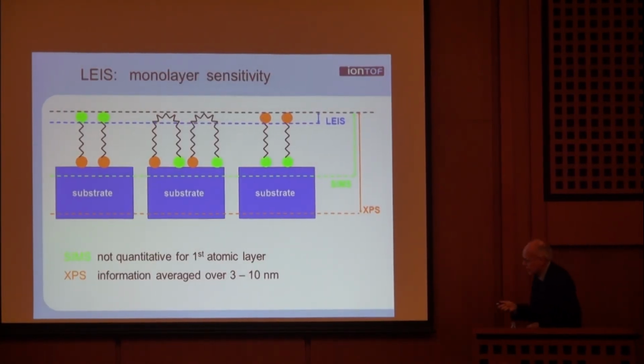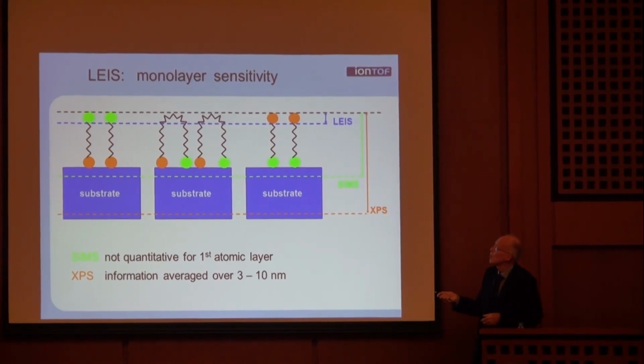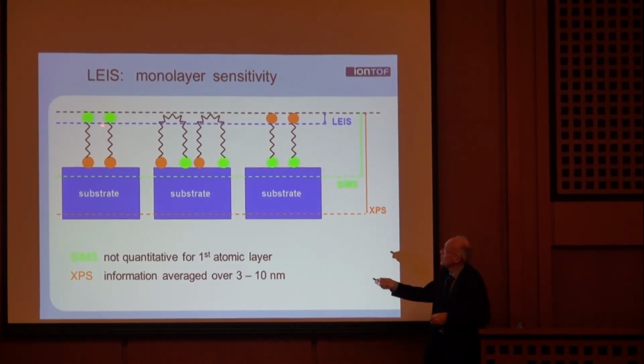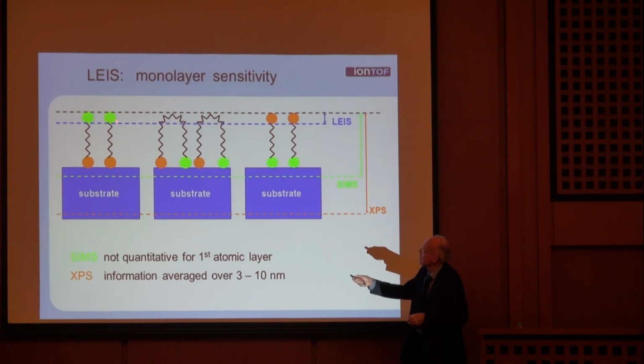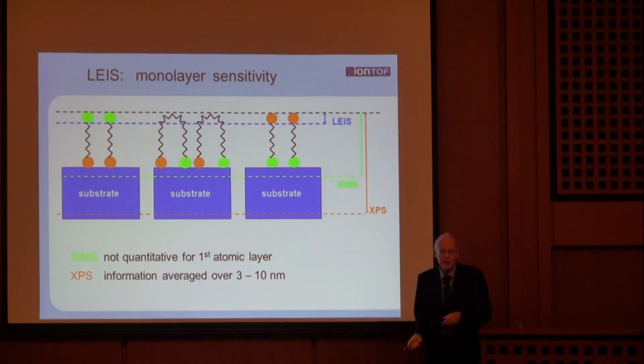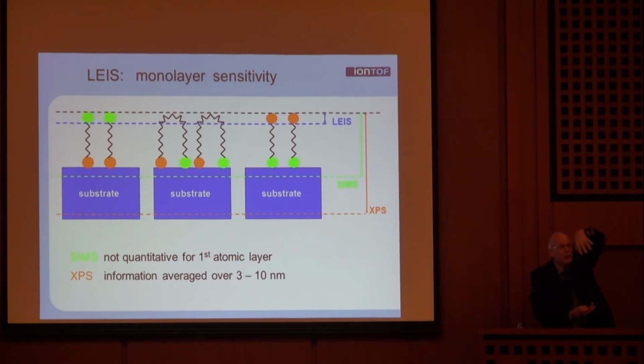If you do organics, like self-assembled monolayers, we analyze the top layer. So here the yellow ones, here the backbone, there the orange ones. And so it is very complementary to other techniques that look deeper, like SIMS and XPS, where you see, say, maybe the whole molecule. And by combining the two, you understand much more about organic molecules, how they orient and what they do at a surface.